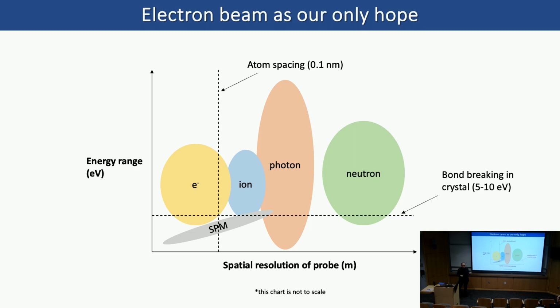So one chemical bond is roughly on the order of 1 eV, and if you have several of them connecting to an atom, those atoms are tightly bonded in the crystal with 5 to 10 eV of energy. So if you want to really break the bond of these atoms, you at least need an energy range that's above 5 to 10 eV.